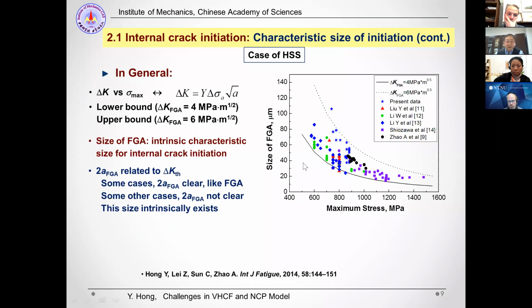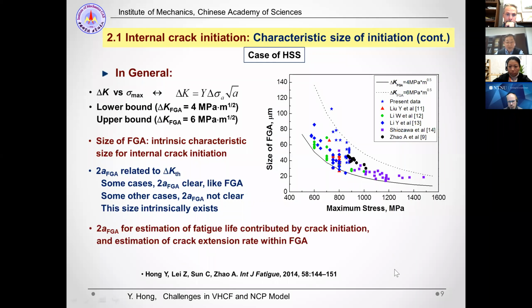So we proposed the size of FGA, this initiation region during very high cycle fatigue, is an intrinsic characteristic size for internal crack initiation. And then we can use this size for the fatigue life estimation and for the crack extension rate in the initiation stage. That's what I said for the crack initiation life prediction and crack extension rate estimation.